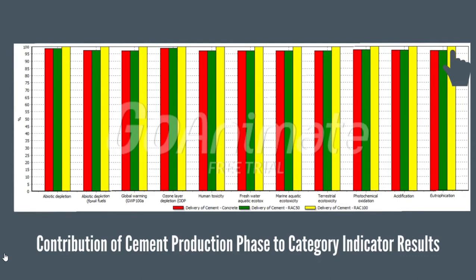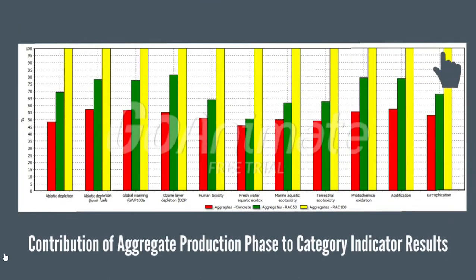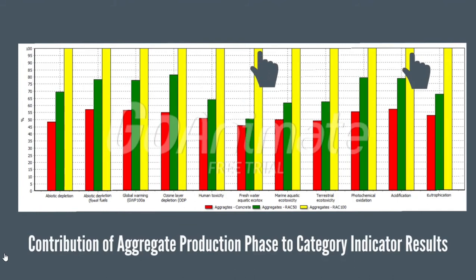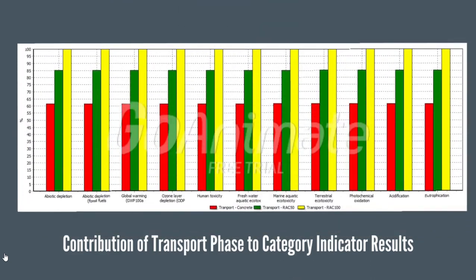REC-100's higher impact is due to its design mix requiring a higher amount of cement. REC-50 and conventional concrete resulted in the same contribution of cement production for all category indicators because they both require the same amount of cement in the design mix; however, there is a slight difference of not greater than 5%. REC-100 contributed the highest in all category indicators for the aggregates production phase since the production of RCA requires additional processes such as crushing. There is an 18% to 50% difference between REC-50 and REC-100 because 50% of REC-50 is from natural aggregates, which have lesser processes in production. Likewise, conventional concrete has a lesser percentage in all categories compared to REC-100, ranging from 45% to 55%.